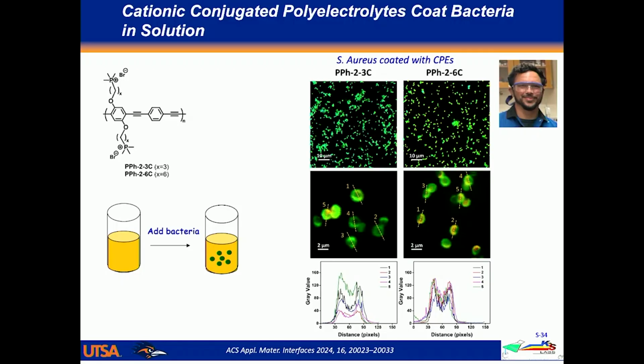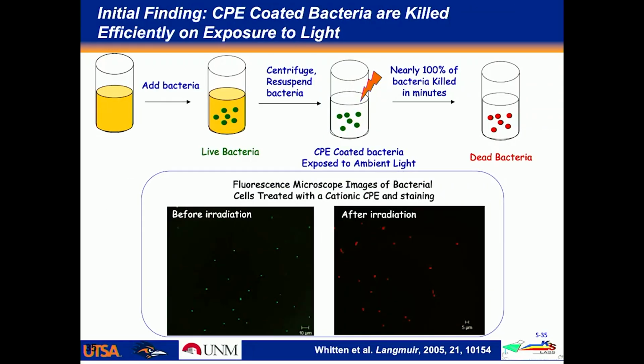If you look very closely, Staph aureus are like little spheres, and it turns out that the green fluorescent polymer is coated on the surface of the bacteria, and you can see that from line scans. If you do a scan through the bacteria, you see the fluorescence peaks around the periphery, so it's coating the surface of the bacteria.